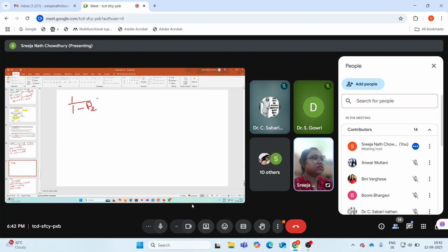Next, the 22.1 problem. The polymerization between equimolar amounts of diol and diacid. Equimolar amount, here is the catch. Diol and diacid with an equilibrium constant of 100 and initial monomer concentration is 2 mole. The reaction is carried out in a closed system without removal of the byproduct.